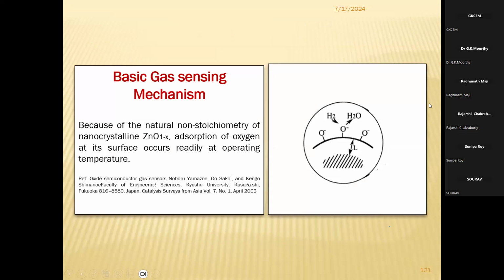So this is the basic gas sensing mechanism. Due to natural non-stoichiometry, if you take a metal oxide such as a zinc oxide layer, the zinc oxide is not complete. This is inherent, God gifted. There is natural non-stoichiometry present in the metal oxide layer or any deposited chemical material. This is metal oxide in my case, as we are dealing with gas sensors. So due to this natural non-stoichiometry, the ambient oxygen present in the atmosphere gets adsorbed on the surface, because the zinc oxide will try to complete itself by taking oxygen from the atmosphere.